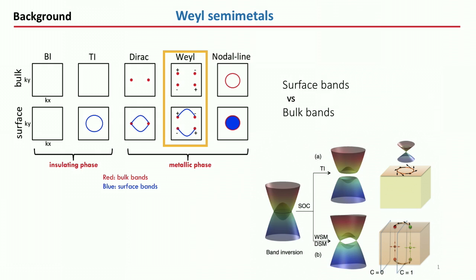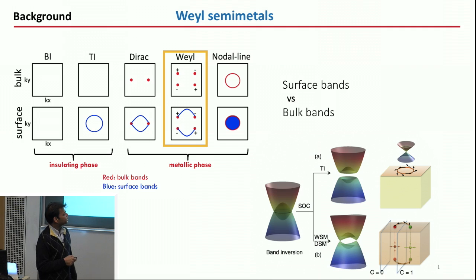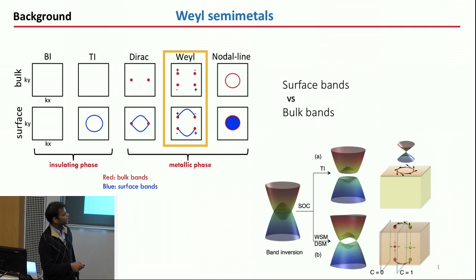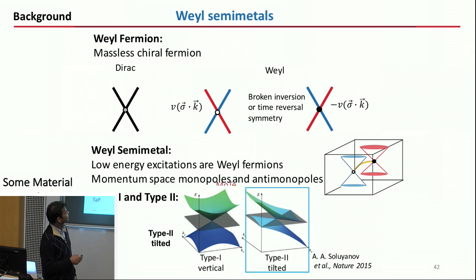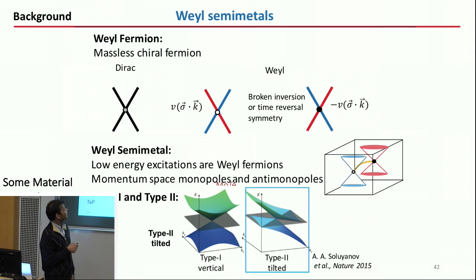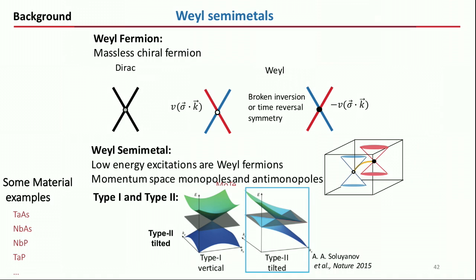So a few years back, there was this discovery that you can get these three-dimensional topological dispersions in what are called Weyl semi-metals. And because of that you have this unique Dirac dispersion in three dimensions. I won't go through the details. But the important thing here is what happens in a Weyl semi-metal: you start with a Dirac dispersion, and then you break a symmetry, either inversion symmetry and or time reversal symmetry. And then you split this Dirac cone into what are called two Weyl cones. And now they have unique chirality. So one cone has fermions which have one helicity and the other cone contains the other helicity.